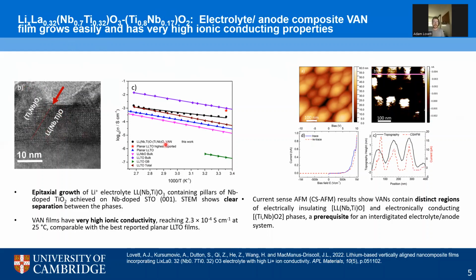From impedance, we observe a very high ionic conductivity, in fact, on the same order of magnitude of the best available LLTO films. This is significant because it is known that doping niobium into LLTO lowers the ionic conductivity of the phase. So in our system, we can retain the high conductivity by compensating for the lowered conduction of the phase by increasing it with the VAN structure.